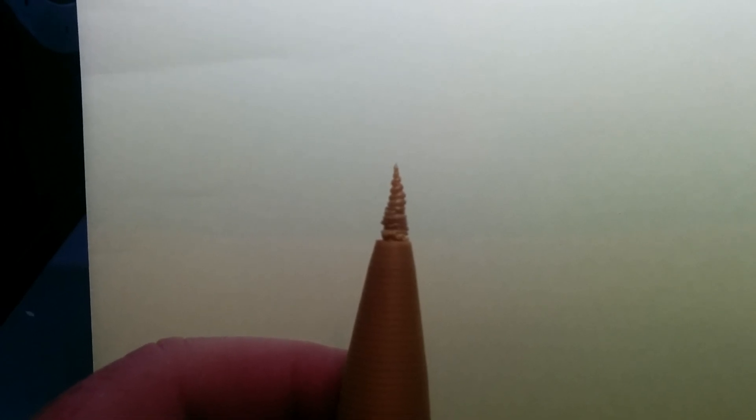And that got me to think, why did it do this? I mean, it's still pointed, but obviously not what it's supposed to look like. I think it's kind of the dwell problem because the hot end touches it. It's not having a lot of air coming across it. So it kind of just melts it up and goops it up and builds on top of each other. So one did not turn out well.